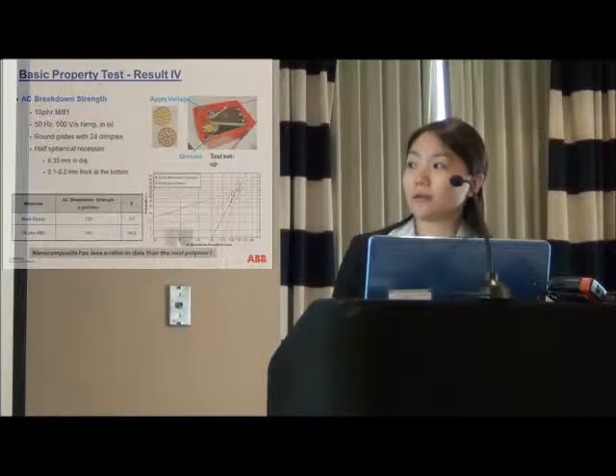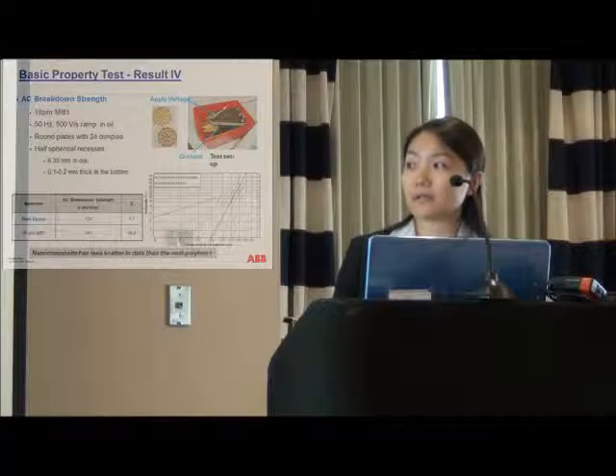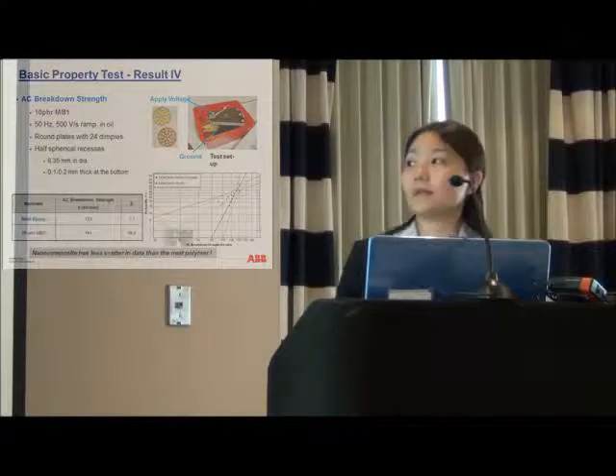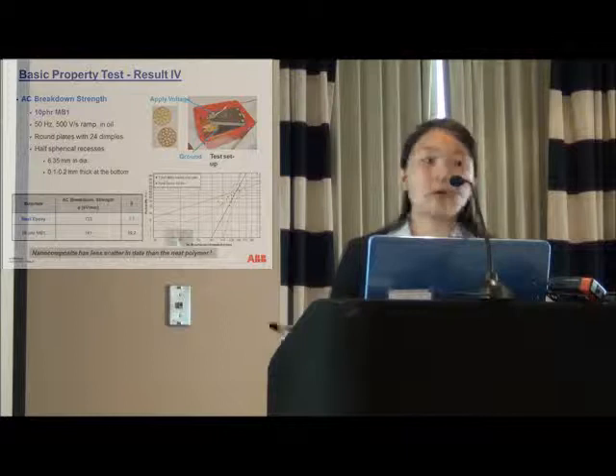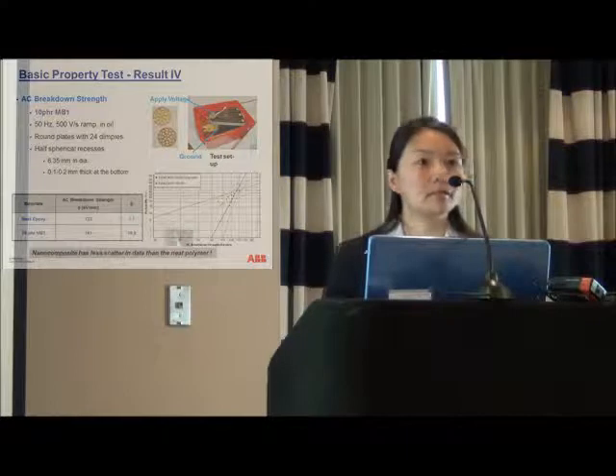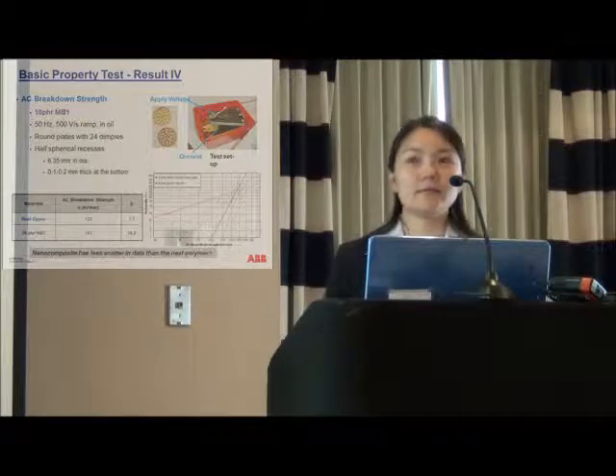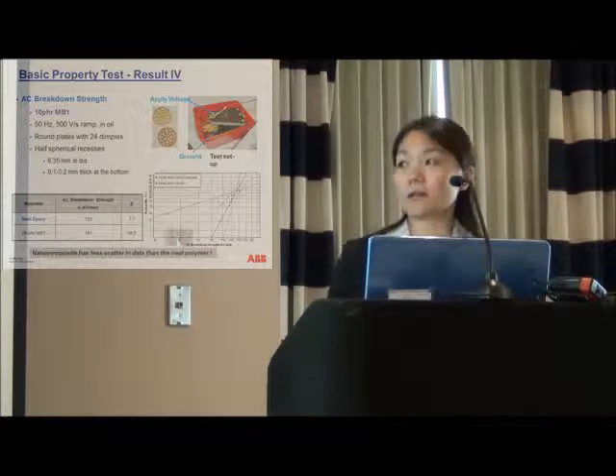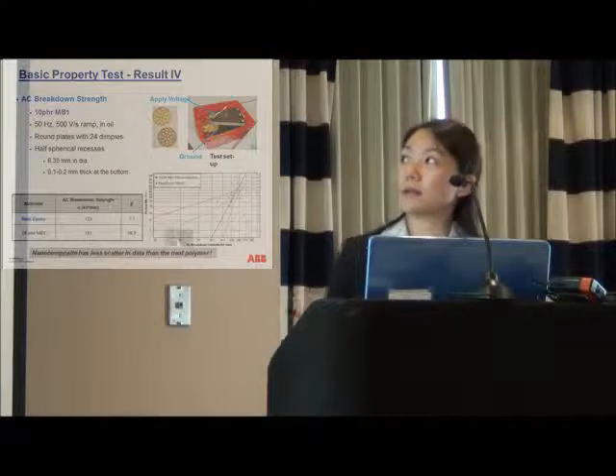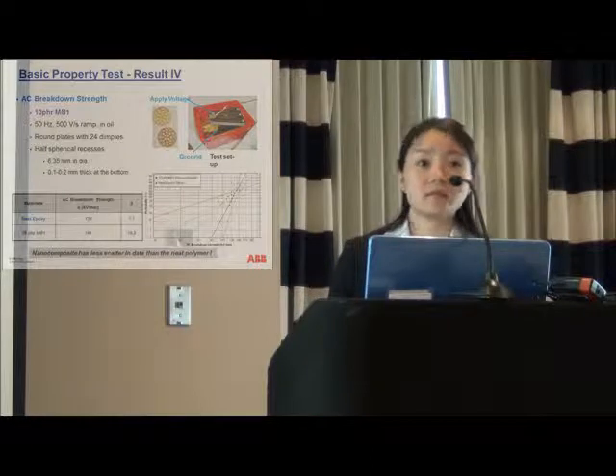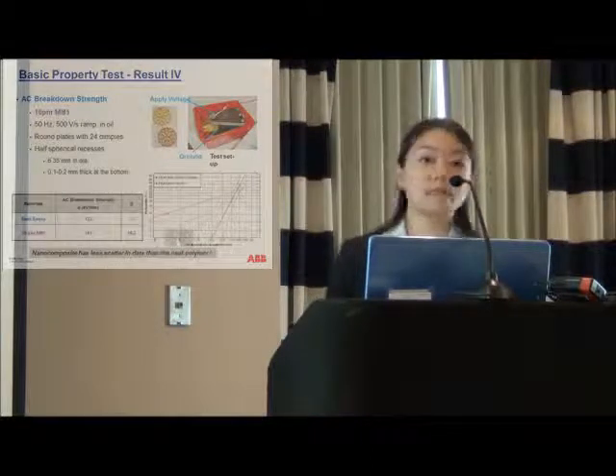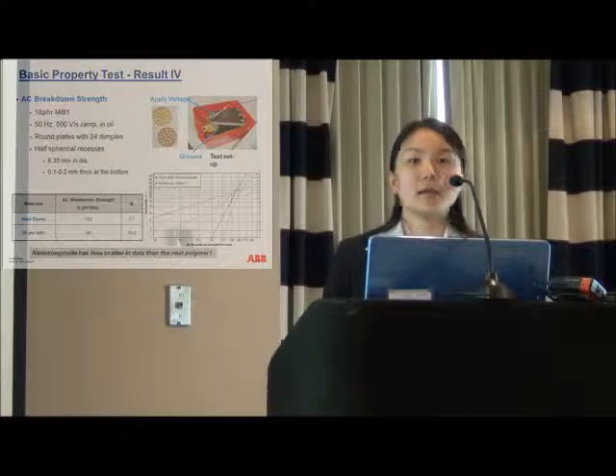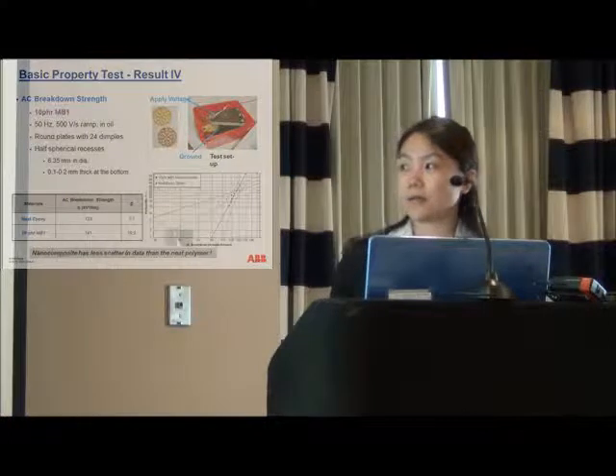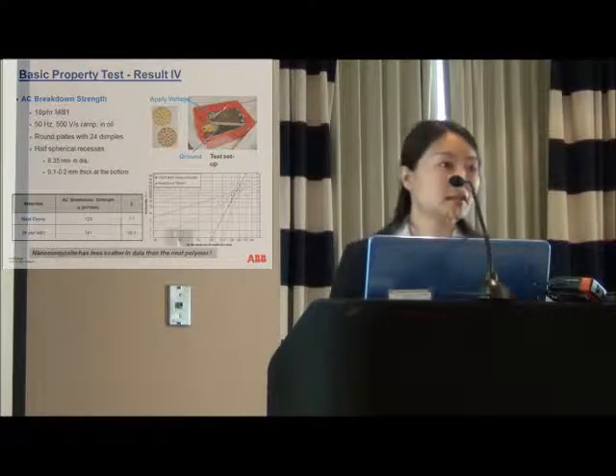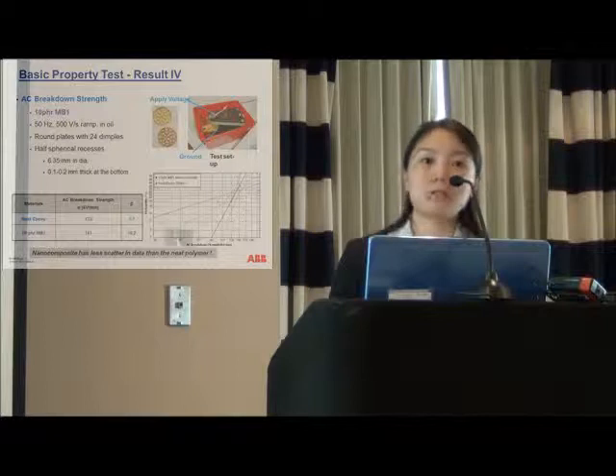But if you look at the beta value, for the nanocomposite it's significantly higher than the neat polymer, although both are not as high as reported in other literature, indicating our method is not perfect. Still, you see the trend that for the nanocomposite the beta value is higher, indicating less scatter in the data compared to the neat polymer.